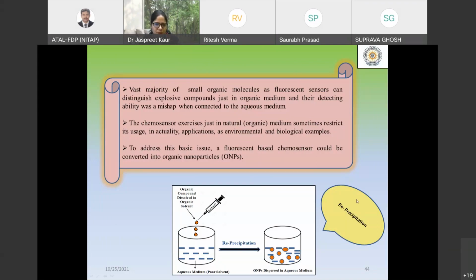So for this purpose, our research group has used the reprecipitation technique for the synthesis of organic nanoparticles. So these organic nanoparticles can be made by using this technique. In this case, we dissolve the organic compound in a particular organic solvent like DMSO or DMF, in which we have got the maximum fluorescence. And then after that, it is dropped into the aqueous medium, and during the addition, it is further sonicated. And after the sonication, the reprecipitation occurs and the organic nanoparticles are obtained, which are dispersed in the aqueous medium.